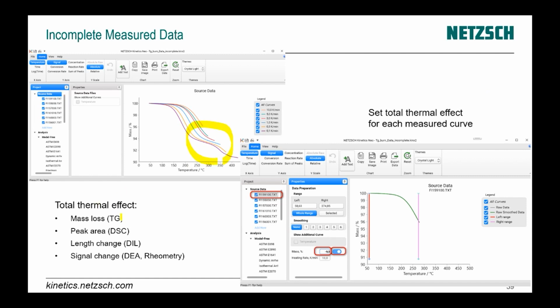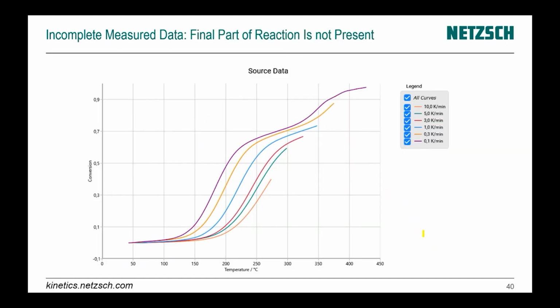Then for each curve, we can put the value of the total effect. For example, it could be total mass loss for TG, or total peak area for DSC, total length change for dilatometer, or total signal change for DEA or rheometry. And here we have a final curve, and finally we can find the degree of conversion as a function of temperature or time for the curves where reaction is not measured completely.